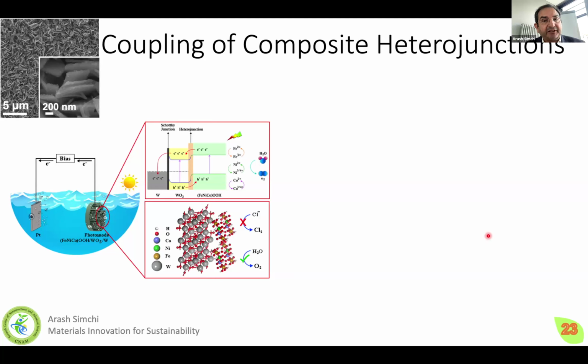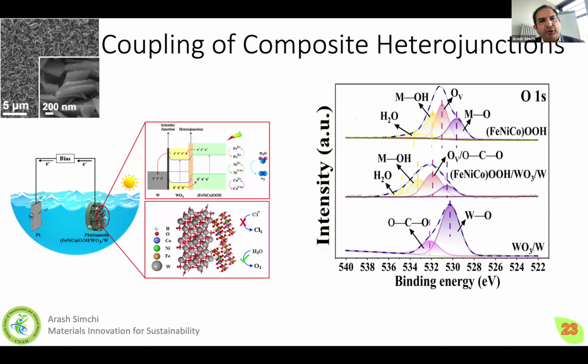We design such a catalyst as you see here. We design a catalyst based on transition metal oxide hydroxide. We put a porous tungsten layer underneath. Then we developed a tungsten oxide nanosheet on the top, and then deposited the multi-cationic transition metal on the top. Just to show you, the process is very simple. It's a simple hydrothermal electrodeposition process. I don't want to go through the fabrication processes. It is available in our publication list. Just take the point. I would like to show you what is going on.